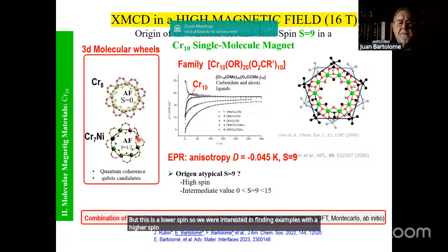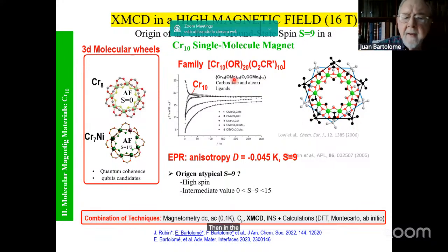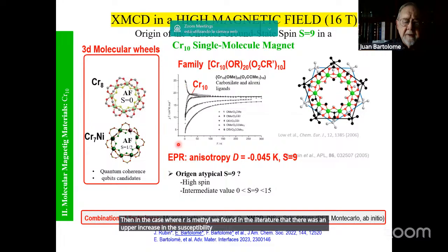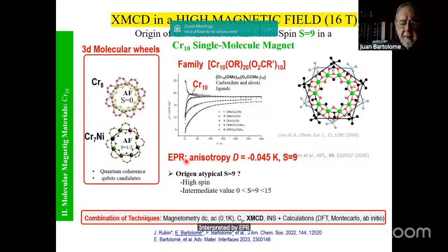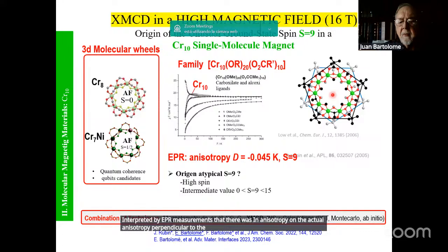So we came across an experimental study of the family of chromium-10 systems, where the chromiums were also organizing themselves in a wheel. Then, in the case where R is methyl, we found in the literature that there was an upper increase in the susceptibility, which was later interpreted by EPR measurements as an anisotropy, a uniaxial anisotropy, perpendicular to the plane of the wheel, and with a spin 9.